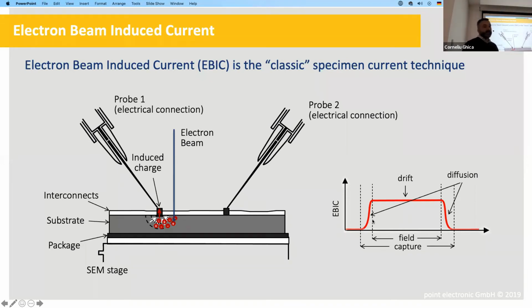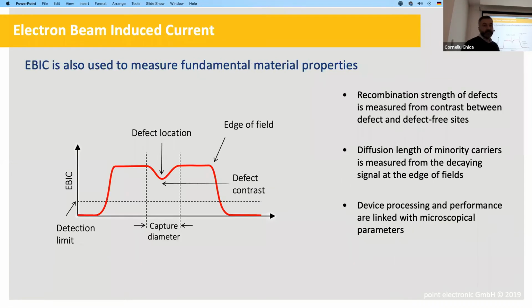So it gives us an opportunity to map electric fields. We can see where they're on the device, but it also gives us an opportunity to understand and localize defects. So by defects in EBIC, this would be defects in the semiconductor. So we're talking primarily about dislocations, grain boundaries, stacking faults, and so on.